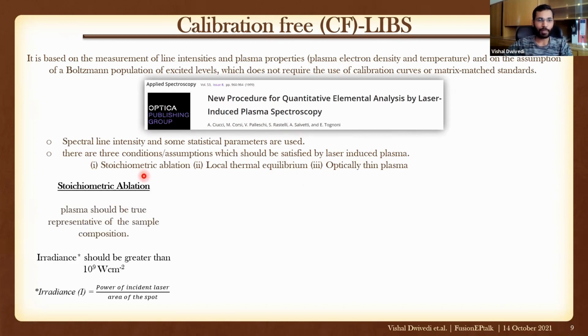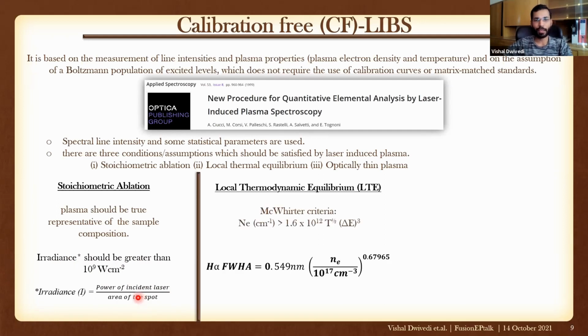So for stoichiometric ablation, plasma should be a true representative of the sample composition. For this, we can verify with this formula. Irradiance should be greater than 10 to the power 9 watt per centimeter square, and irradiance we can calculate using this formula. Local thermodynamic equilibrium, for this we have the McWhirter criterion. So electron density should be greater than this particular value, where we use the temperature and energy gap of the upper and lower energy states.